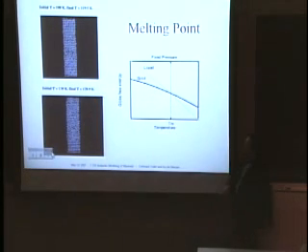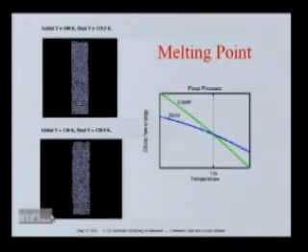So once you believe iron, now the issue is trying to figure out its phase diagram: at which temperature you have coexistence between the solid and the liquid. And you have actually done this in your laboratory 4, an explicit method to find the transition temperature by doing a simulation of a liquid and a solid phase and figuring out at which temperature the boundary between the two phases doesn't grow into each other. So the solid doesn't keep growing or the liquid doesn't keep growing. And you see an example of this in what follows.